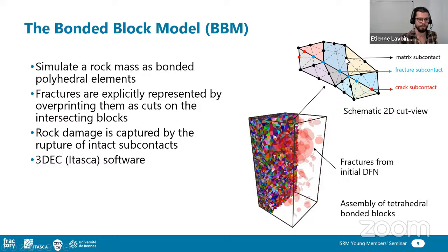And we also embed the fractures in this kind of model. So the fractures are represented by overprinting cuts on the intersecting blocks, so that in the end, you end up with subcontacts that are assigned matrix properties and fracture subcontacts that are assigned fracture properties. And the matrix subcontact may fail if the stress is sufficiently high, and then the fracture properties are assigned to this subcontact that we call a crack subcontact. So the rock damage is captured by the rupture of intact subcontacts.